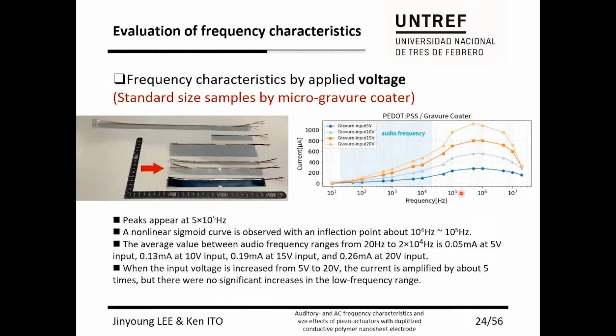Peaks appear at about 500 kHz, and a nonlinear sigmoid curve is observed, with an inflection point at approximately 10 kilo to 100 kHz. The average of the current amplitude between audio frequency range from 20 to 20 kHz shows that the current is amplified 5 times greater when the input voltage is increased from 5 to 20 volts. From this point, we expect that increasing the voltage will enhance the audio signal. However, there were no significant increases in the low frequency range.